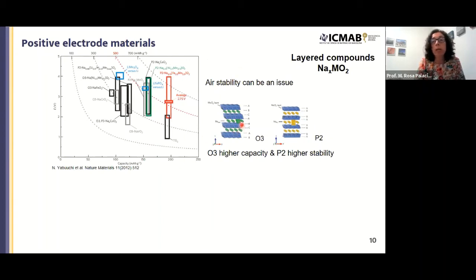The first are very similar to the lithium cobalt oxide I was mentioning for lithium-ion batteries, which nowadays has also diversified a little bit. In some cases, instead of only cobalt, we have nickel and manganese as well, the so-called NMC. They have a layered structure with edge sharing metal oxygen octahedra, and in between the lithium ions are also coordinated, typically octahedrally, or in some cases also tetrahedrally.